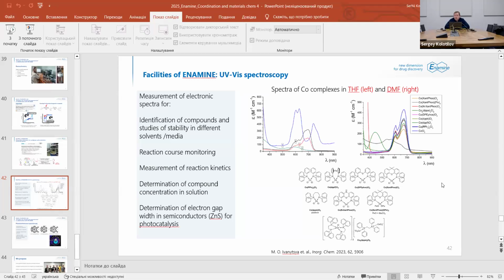Also, we can make studies of electronic spectra, and using this technique, we can make identification of compounds and study of stability in different solvents. For example, on the slide, you see spectra of a series of cobalt complexes. Left one in THF, tetrahydrofuran, and right one in DMF, dimethylformamide. So you can see that in DMF, all spectra are almost the same. It's a sign that these compounds are decomposed. But in THF, they are stable.